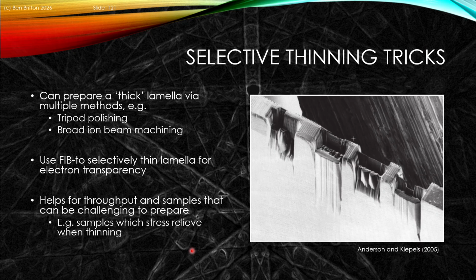One of the other bits you can do is you can be clever about how you do the thinning. And so what you might want to do is, for instance, prepare a significant extent of wall of your structure, and then you can cut out a series of electron transparent windows at different thicknesses through your object. And that can be particularly useful if you want to look at a layered structure, or you want to manage things like residual stress or other such, or have multiple samples, where you could, for instance, use a wedge-based macroscopic polish to produce the wedge, and then use the FIB just to make the localized, very thin, constant thickness cross-sections. And so that wedge polishing is done with a tripod polish or broad ion beam machining with cross-section, and then you use the FIB to selectively thin the lamella from that region. It's not as site-specific because, of course, the sites are all located on the edge of the object, but you can get significant throughput enhancements with this.